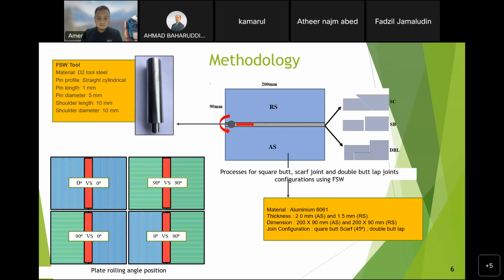The material used for this friction stir welding comparison is aluminium 6061. The thickness for the advancing side is 2 mm and the retreating side is 1.5 mm. The dimensions are 200 by 90 mm. The three types of joint configuration for the comparison are square butt, scarf, and double butt lap joint.